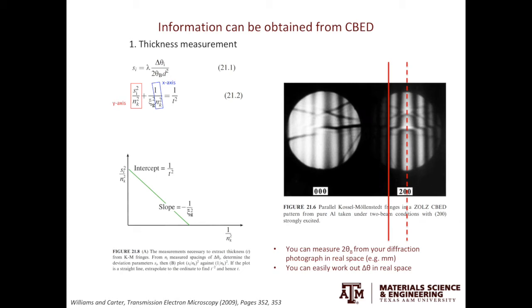What this tells us is if we put S1, S2, and S3 into this equation, they should form a straight line. Coming back to Nk. For Nk, if we select three S values, we can assign Nk as 1, 2, and 3 first. If it does form a straight line, then we can calculate the T value, the specimen thickness, straight away.